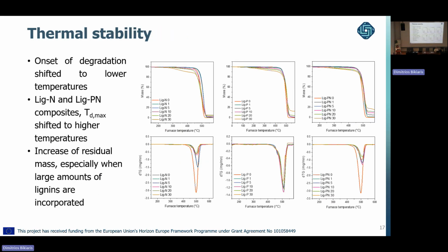Now, thermal stability. Here we can see that for all composites, again, the degradation starts a bit earlier than without lignin. Nevertheless, in the composites which have been modified with nitrogen, the temperature of the highest degradation rate is shifted to higher temperatures compared to neat HDPE, while when we have inserted phosphorus in the composites, we have a significantly increased residual mass at 600 degrees.